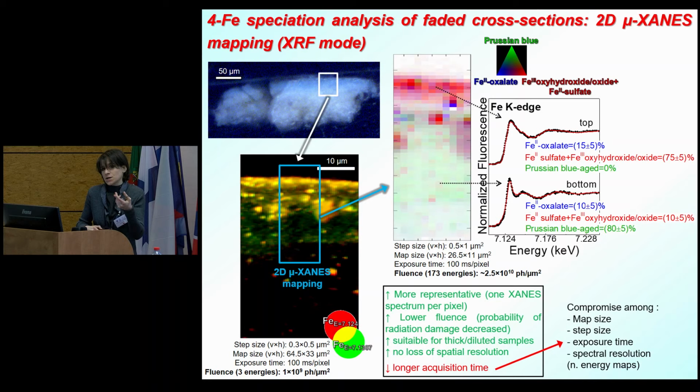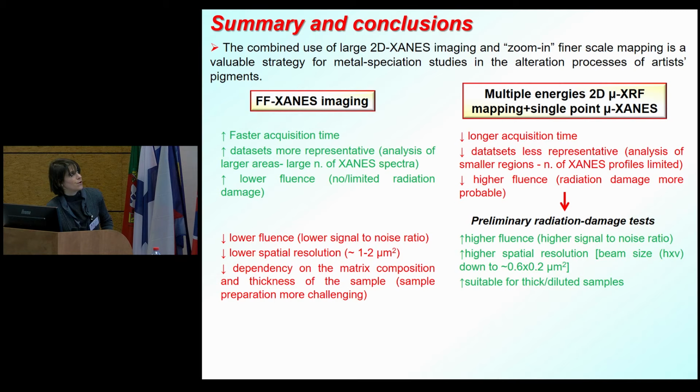Of course, the disadvantage is the longer acquisition time. So every time we have to find a good compromise in terms of map size, step size, exposure time, and spectral resolution. In concluding, we can say that the combined approach of large 2D XANES imaging spectroscopy experiment in transmission mode, and zoom-in fine-scale mapping in X-ray fluorescence mode is a valuable strategy for studying the alteration mechanism